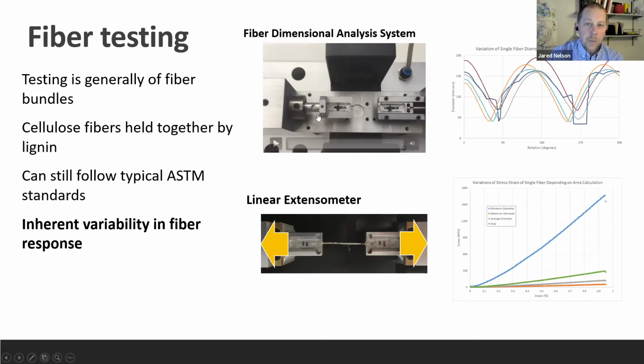So again, this is a key piece of equipment because it gives us that cross-sectional area information that then allows us, when we place that same fiber into this linear extensometer and then pull it in tension and break it, we can then convert the data that we're getting from that to stress and strain. And we can do that as shown in this figure here. This is a stress strain curve for a particular fiber, and this is calculating the stress utilizing different cross-sectional areas depending on what we see here. And so it can vary significantly from that point.